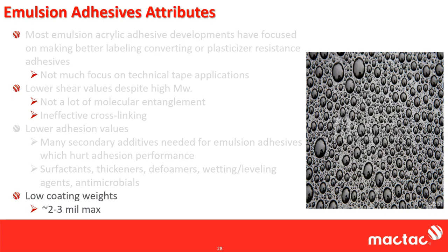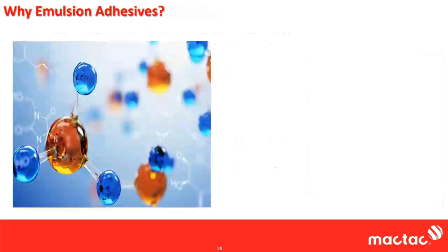Above that, it becomes a law of diminishing returns, and you start skinning it, and you can't get them dry. So with solvent-based adhesives, you can get 5 mils. With water-based, 2 mil, maybe 3 mil if you're willing to tolerate a lot of residual moisture. So why emulsion adhesives? There had to be a reason why they came about.